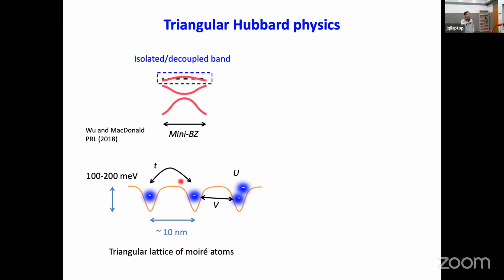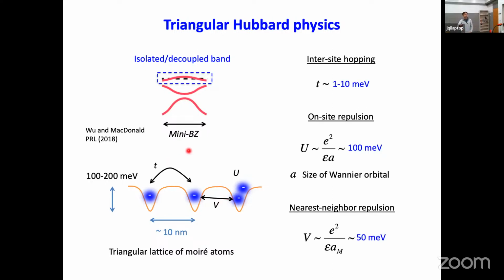And then the electron can hop between sites with an amplitude t. And if you happen to put two electrons on the same site, they Coulomb repel each other with energy U. They also experience the intersite Coulomb repulsion V. Okay. And to give you a sense of the energy scale, t is typically 1 to 10 milli electron volts for the kinetic energy of the electron. And U, you can estimate using the size of the Wannier orbital in this material, is on the order of 100 milli electron volts. And for V, you can use the Moiré period and the dielectric constant of the surrounding dielectric to estimate an energy scale of about 50 milli electron volts for the nearest neighbor Coulomb repulsion. You can see that the Coulomb repulsion energy scale actually dominates over the kinetic energy scale of the electron in this kind of system. So we have strong correlation physics quite easily seen in experiment.